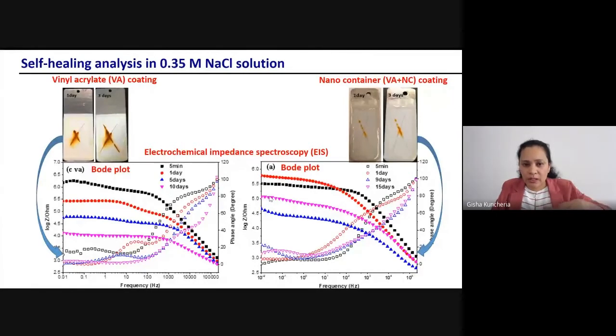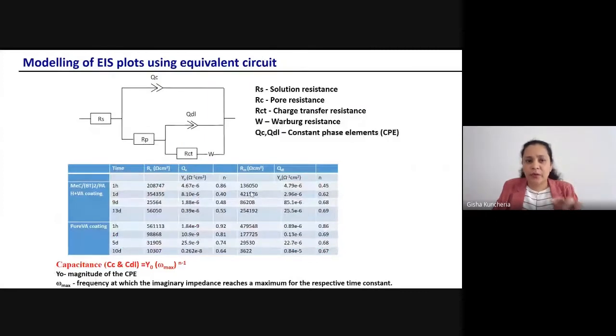What is the meaning? The impedance decreased, which means there might be electrolyte ingress through the coating. That's the reason it decreased. But after some point it started to increase. That means the coating is retained, its integrity or its anti-corrosion behavior. So to get a complete idea about what happened on these coatings, we can model these Bode plots using an equivalent circuit.